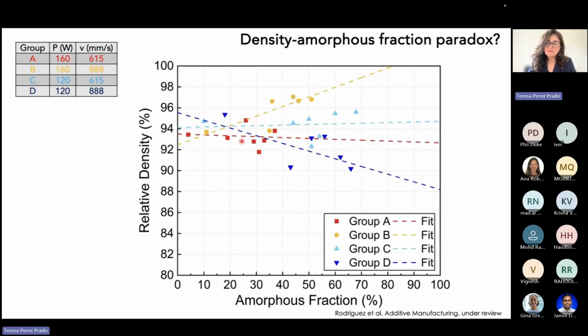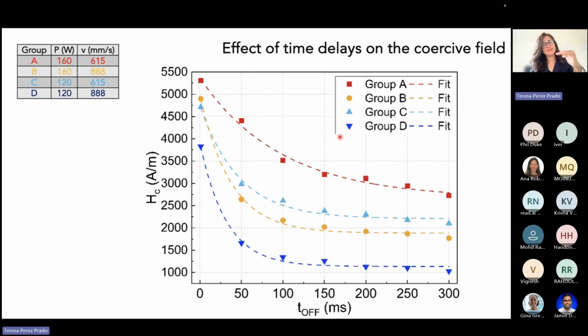And then, even in conditions light blue, which is C, and also red, group A, at least the amorphous fraction increases without any major changes in the density. So it seemed like introducing time delays was actually good, but with these commercial alloys, we are still not doing well in terms of the absolute values that we want.